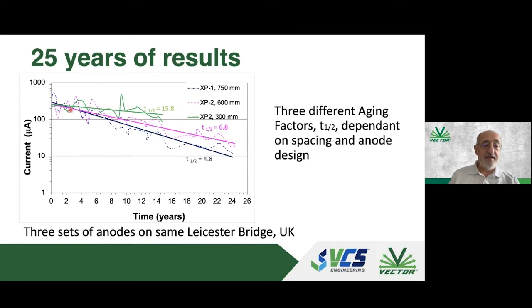And you can see that it started at essentially the same current as the others. But because we are not pushing the anodes anymore, they are lasting a lot longer, and you have a much improved aging factor, so far of the order of about 16 years, which is a huge improvement in performance.